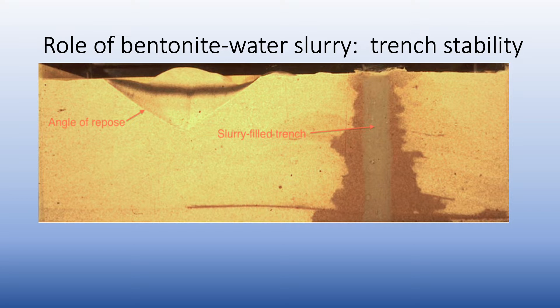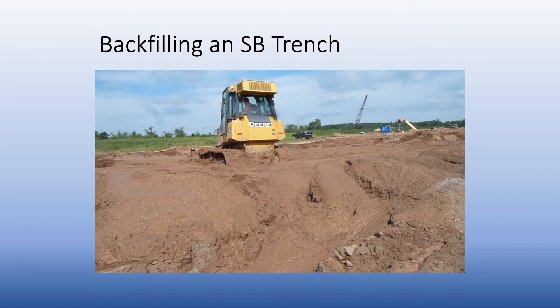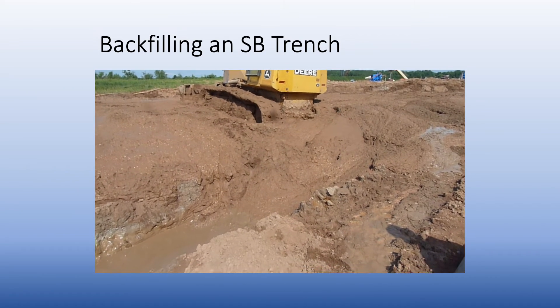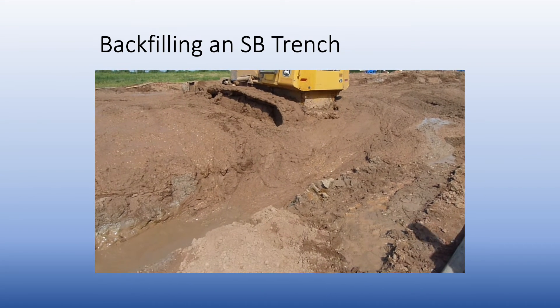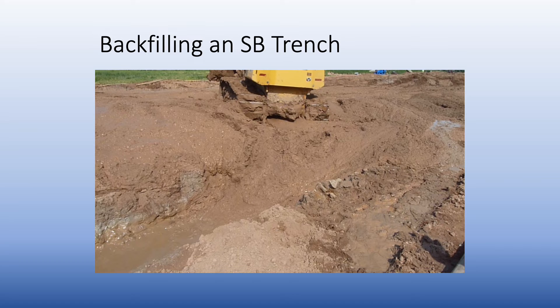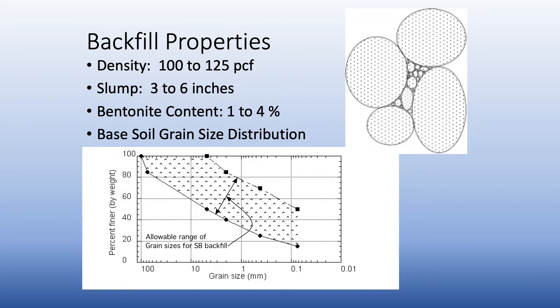In theory, there's no limitation on the depth to which you can excavate. Once the trench is excavated and slurry-filled, the slurry needs to be displaced with the backfill. The schematic shows how the backfill slides down the trench and displaces the bentonite water slurry in front of it. The best mixture for this backfill uses a well-graded base soil consisting of gravel, sand, and silt-sized particles.